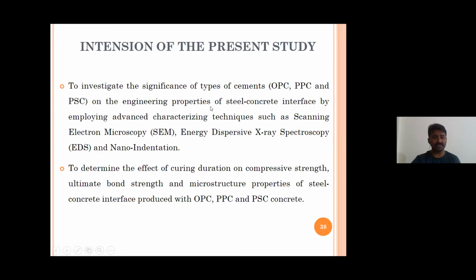What do I mean by engineering properties? One is what is happening to the porous zone thickness, what is the effect on the hydration products which are formed at the steel concrete interface, and what is the total influence on the bond strength. So these 3 parameters, I am converging them and terming them engineering properties. Second one is to determine the effect of curing duration on compressive strength, ultimate bond strength, and microstructure properties of the steel concrete interface produced with OPC, PPC, and PSC concrete. That was the focus of our study.